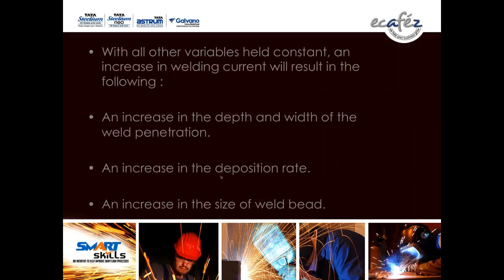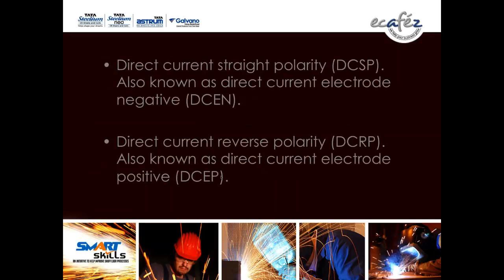With all the other variables held constant, an increase in welding current will result in an increase in the depth and width of the weld penetration, an increase in the deposition rate, and an increase in the size of the weld bead. Next is polarity. Polarity may be of two types: DCSP or DCRP, DC straight polarity or DC reverse polarity. DCSP is also called DCEN, and DC reverse polarity is also called DCEP.